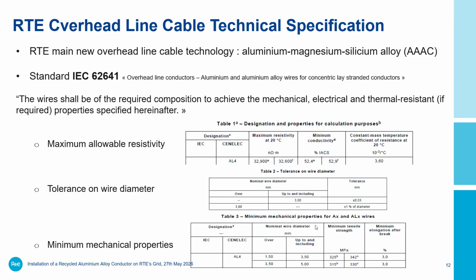The first one is about our TSO specification. One important thing is that in France, our main technology that we are still installing on our network is a AAAC cable, meaning that we use aluminium with another element. It's an aluminium alloy, so this material is less sensitive to the introduction of some impurities. On our specification, we refer to international standards. We want mechanical, electrical, and also thermal properties. Concerning the electrical properties, we put some maximum value that we do not want to go above. So it's a maximum resistivity.